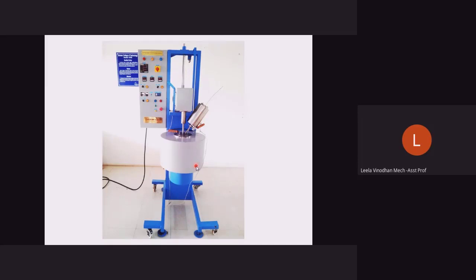And one more to add to this particular technique: what we generally do is take the casting and then pre-treat it. You can maintain it at a particular 400 degrees Celsius or 500 degrees Celsius in the furnace, especially in an argon atmosphere or whatever gas you can have. So that is also going to give you a different result, not only the casting. After that also you can go for pre-treating and then do the heat treatment. That is also going to fetch us different properties.